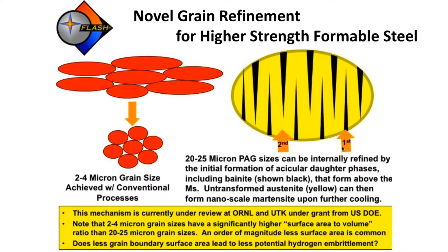Now, one other interesting concept that's further under investigation is the larger your grain sizes, the less grain boundary surface area per unit volume. Will that lead to less potential hydrogen embrittlement, since hydrogen actually migrates on grain boundaries? Well, I can tell you for sure we've never seen any delayed cracking, and we do have parts here that are 6 or 7 years old and shipped out display samples to well over 100 people at trade shows, and nobody's ever come back and said we had delayed cracking or seen evidence of hydrogen embrittlement. So a good thing over time, I guess.